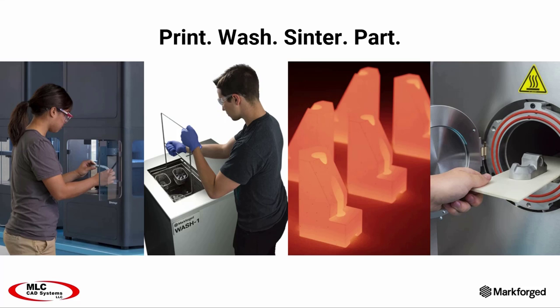After sintering and cooling down, those metal particles have diffused together and the part has densified to a 99.8% dense material, which is going to be equivalent to a billet material. Finally, your part comes out of the furnace. This is your post-sinter part. You have a metal part now. This metal part is what we call near net shape. Once the sinter cycle is complete, around a day's time, your part is ready for use. Now let's take a look at Trip, and he's going to go through the entire process from start to finish.